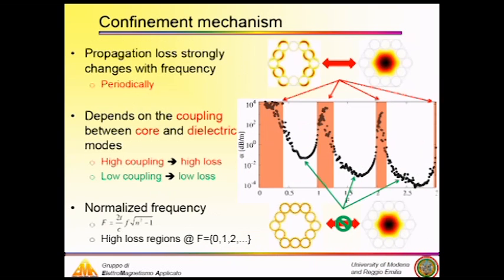And yeah, the propagation loss, as reported here as an example, alternates high and low loss propagation regions. In particular, high loss regions are due to the coupling between the core mode and the dielectric modes, whereas where there's no coupling between these two classes of modes, we have low loss propagation regions. The results have been reported in this picture considering a normalized frequency, and according to this normalization, the high loss regions are placed at integer values of this normalized frequency.